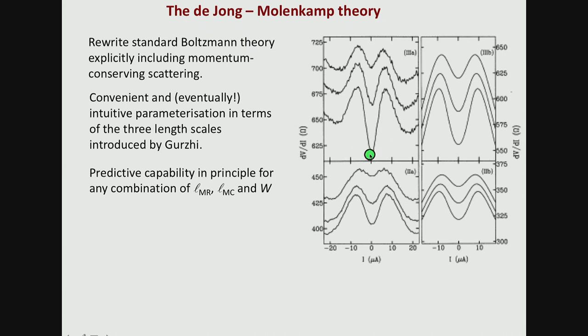So what they're seeing is that they have a certain amount of resistance, and then as they heat the wire up, first of all, the mean free path, they heat the wire up and they create the usual thing that's happening of the resistance going up as you heat a wire, heat electrons. But as they're doing that, the electron-electron length is coming down, so the thing's getting more viscous, and eventually the resistance turns over so that as the wire gets hotter, the resistivity goes down again. And that's that Gurzhi minimum. So basically what's happening there is the wire is getting hotter, so the viscosity is getting smaller. As the viscosity gets smaller, the resistance goes down, the flow resistance goes down for the same given boundary conditions.